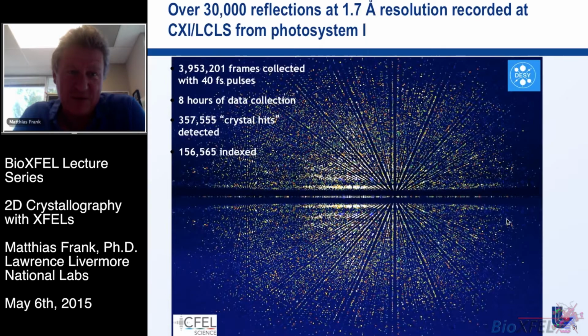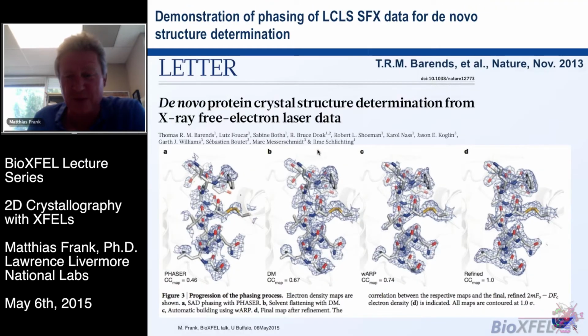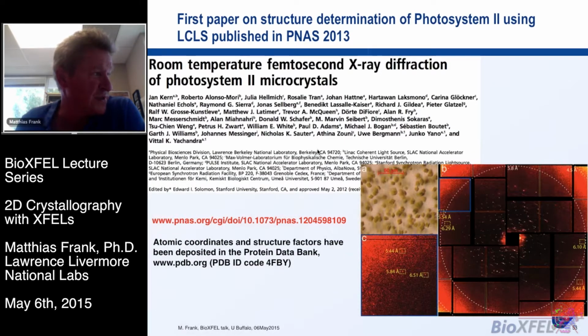And the data set that was produced here for photosystem 1 was collected over, I think, 8 hours of data collection, where almost 4 million frames or images were collected. Not every one of these images, for every X-ray shot, contains diffraction patterns. But out of these almost 4 million frames, 357,000 contained measurable Bragg peaks, crystal hits, and then about a third of those were actually good enough that they could be indexed and used for the reconstruction. So it's a large number of crystal hits that you need, and that's a very different way to take data compared to a larger crystal at a synchrotron, where you maybe measure the crystal in some tens or a few hundred orientations. So the actual number of image frames you use in synchrotron-based crystallography is much smaller than here.